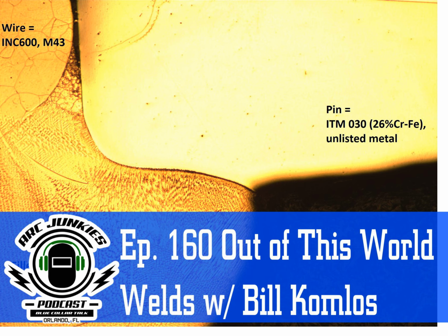So I typically, when I'm testing, use the temp sticks, thermal crayons, because they're within 1 degree accuracy. They'll only give you the melting point. If you're controlling interpass temperature, which nowadays we all know to do, you're also going to have a top end. My big-time welders may be preheating at 225 because we're up to 2 inches thick or something like that. But I've also held them to 550 degrees, and I'm not conservative.